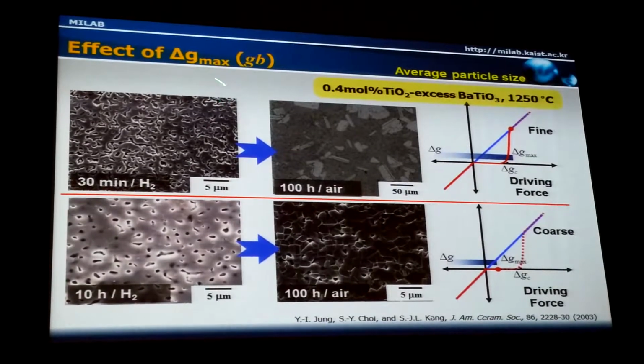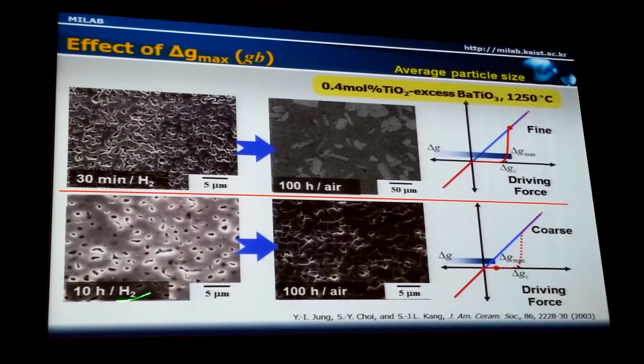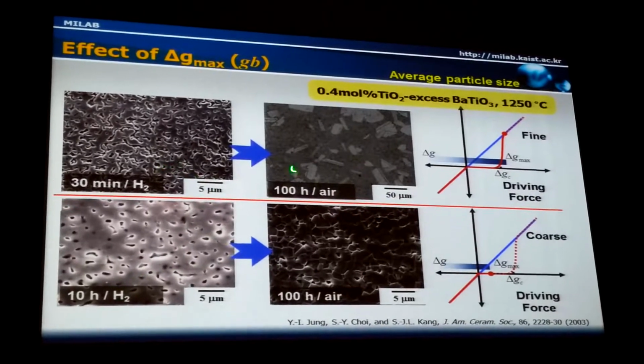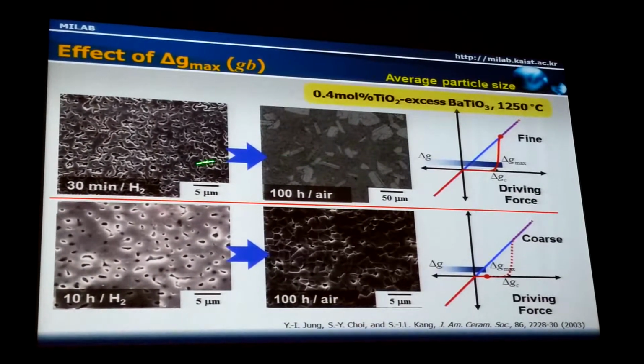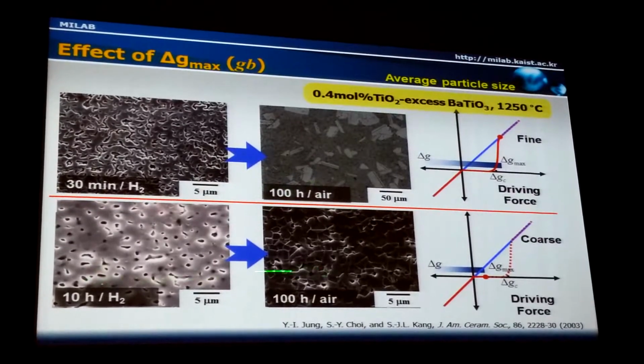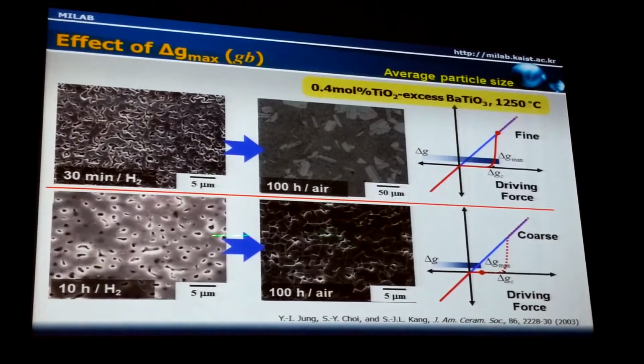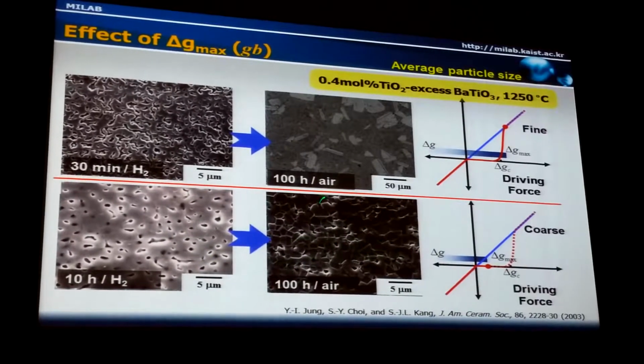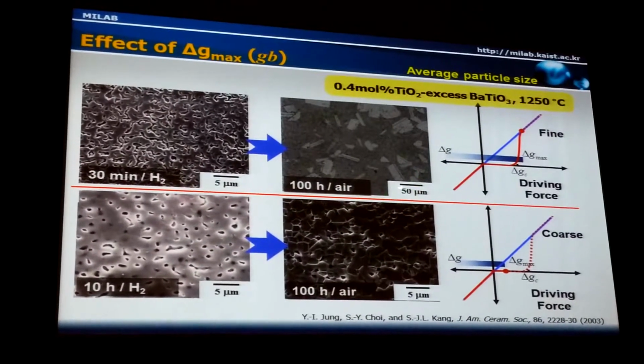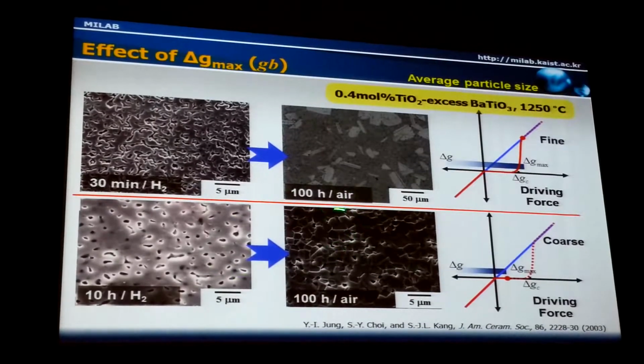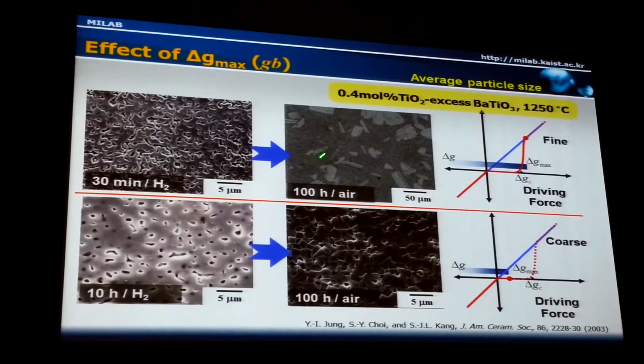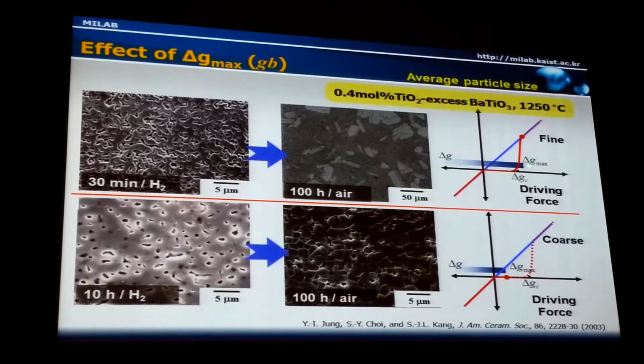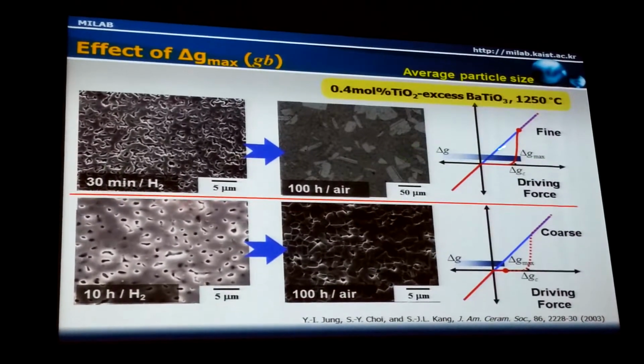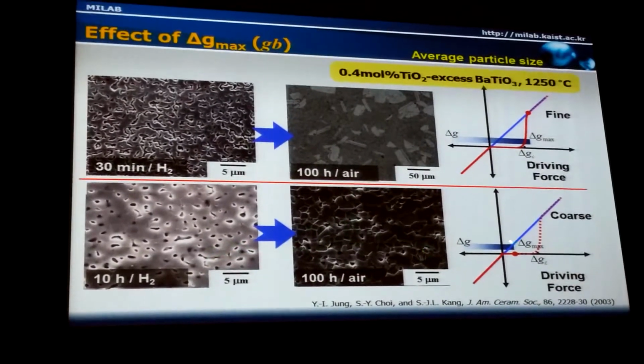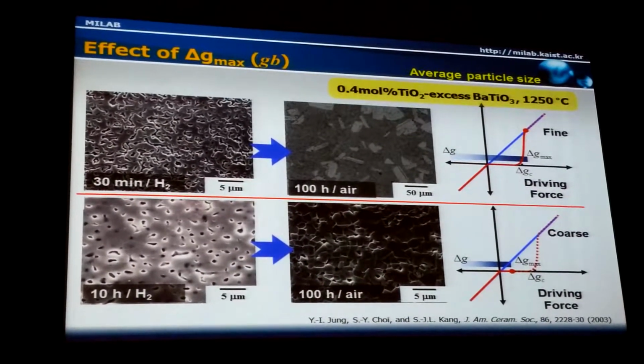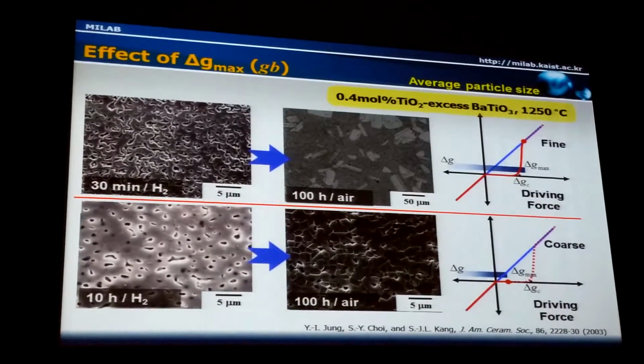First, the effect of the maximum driving force. We start with a fine grain and a coarse grain in barium titanate, and in that case, big abnormal grains form after a certain period of time. But in the other case, there is essentially no change in microstructure. Average grain size didn't change at all. So this experimental result is in accord with our prediction of the effect of the maximum driving force. In the first case, the maximum driving force is large enough, and some of the grains grow appreciably, forming abnormal grains. In the second case, the maximum driving force is smaller than the critical one, and none of the grains grow appreciably.